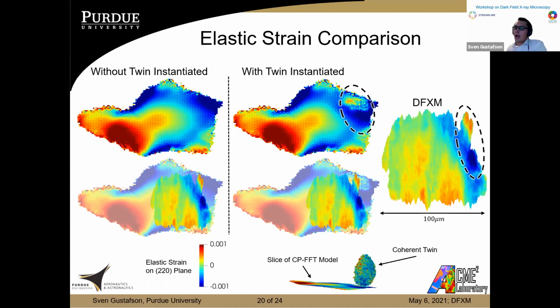of our elastic strains. As a side note, we did see that if you take a line from the high region of elastic strain to the low region, and then convert that strain difference to stress, we're seeing about a 400 MPa jump in stress with just a change of 30 microns within the grain of interest.